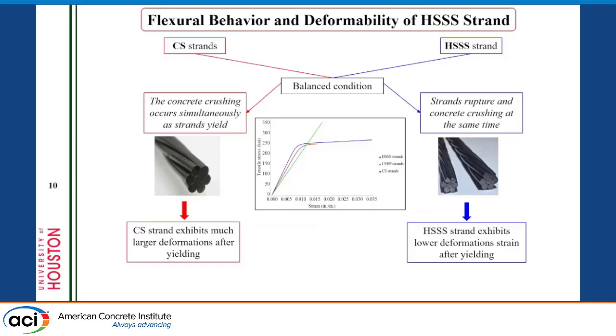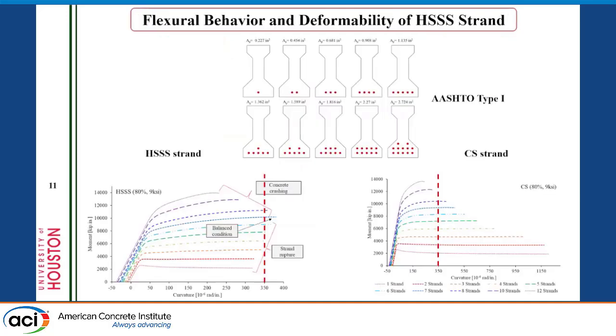It's the same. But for the strand rupture, we need to understand what's going to happen. So this is just some section analysis where I wanted to show the differences between using the stainless steel compared to the carbon steel, and that dashed red line, which is, I mean, they have the same curvature. Basically, we used Type 1 with different numbers of strands, and you could see clearly that for above 7 strands, we have crushing of concrete.